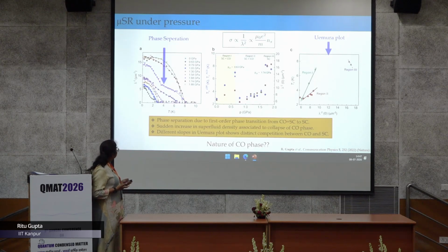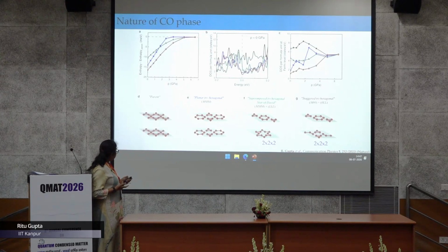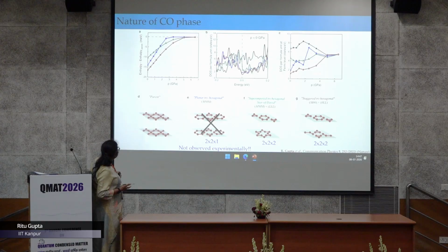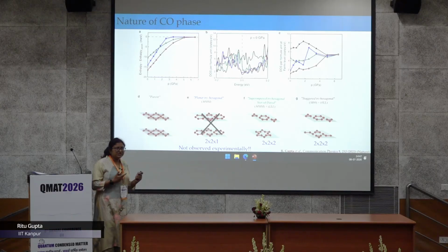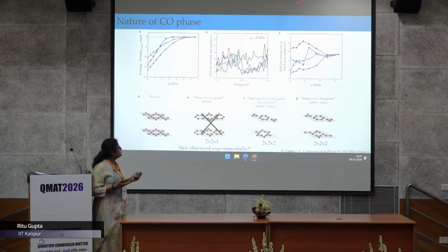And for this it will be 2×2×1, which is not observed experimentally, so we can rule out the possibility for this one. And if we look at the enthalpy difference between the two of them, it is not much. So that means any of the phases can switch into each other within the pressure range we studied.